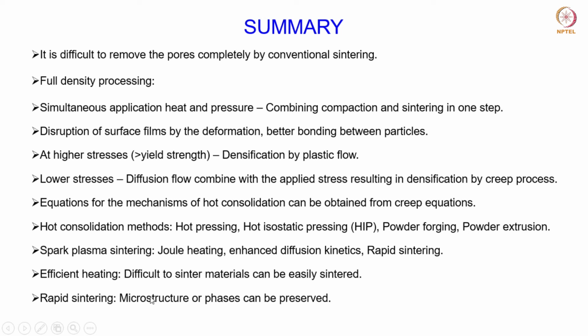Okay, and the rapid sintering which occurs in this case will also allow us to preserve a particular microstructure which may be desired in the final product, or a particular phase which may be needed for achieving certain properties. That can also be preserved with the help of this particular technique called spark plasma sintering, because the sintering time in this case is much lower. It is in the range of few minutes to maybe couple of hours at max, compared to several hours or even days for the conventional sintering process, right? So due to this kind of rapid sintering kinetics, a microstructure can be easily preserved because there is no time for the microstructure to grow or change, as the sintering and the heating and the cooling processes occur rapidly.